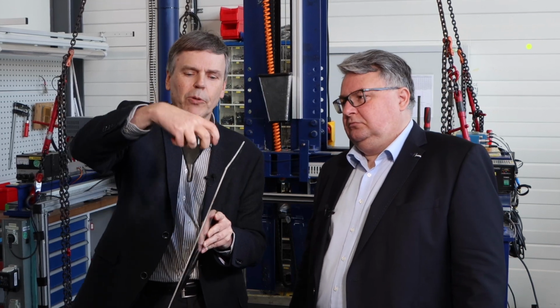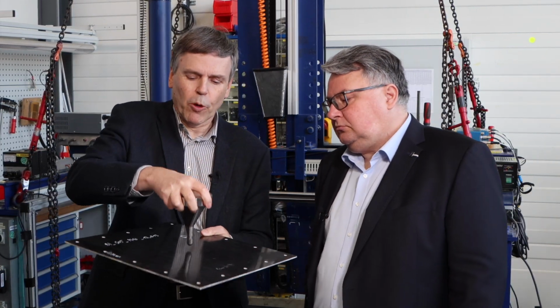And then we cannot use this dart. Then we use a different dart, because otherwise the dart would already hit the edge of the clamping frame. And that's basically because it's more realistic that parts hit at an angle. If you hit perpendicular, it's quite easy to penetrate. It's more difficult when you have some sliding of the dart over the material.